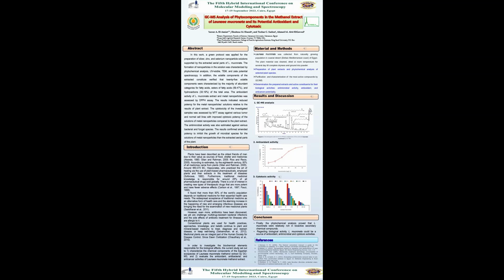Results and discussion. GCMS analysis. The volatile components of the methanol extract of Launaea mucronata were accurately characterized by GCMS analysis. The most abundant molecule was palmitic acid, 12.57%, isolated after 21.65 minutes, followed by 3,14,16-trihydroxycard-20(22)-enolide, 7.92%, and stigmast-5-en-3-ol, 3-alpha, 24S, 7.91%. The results of GCMS analysis have also specified 4 main classes of components categorized as